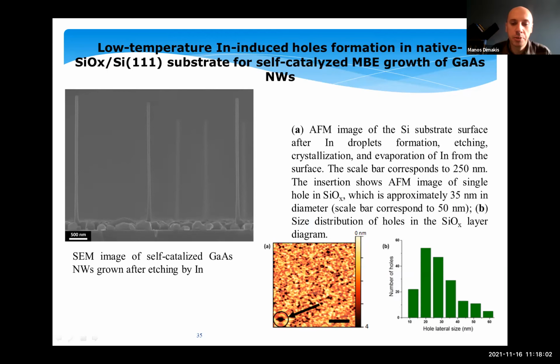Alexei, yes, please. Yes, thank you, Rodion, thank you for the inspiring talk. I have a small question. Since quantum dots have different composition from the mother nanowire, they should create some mechanical stress. And what is the estimated magnitude of this stress? And does it somehow affect the growth of a nanowire itself or luminescence spectra of quantum dot, or the stress can be completely neglected?